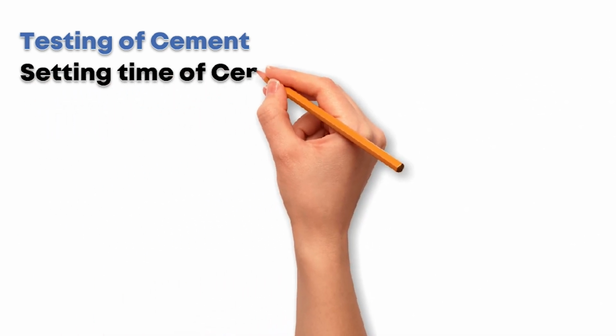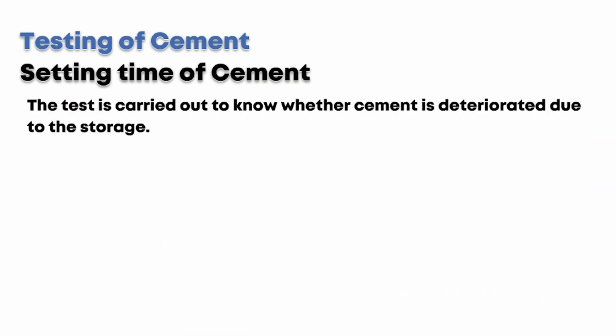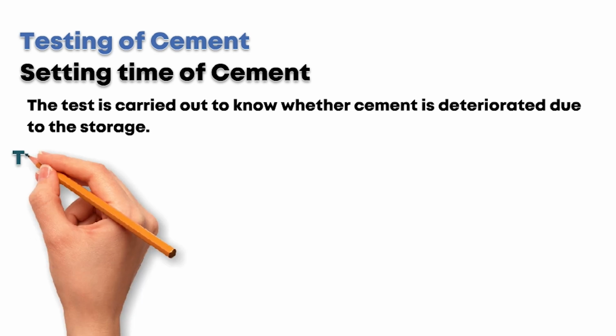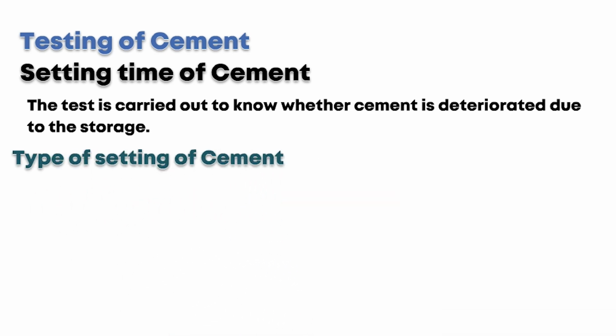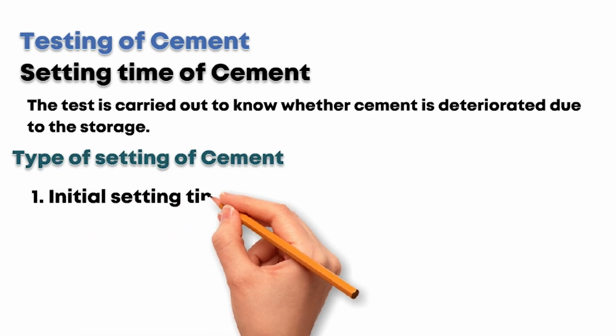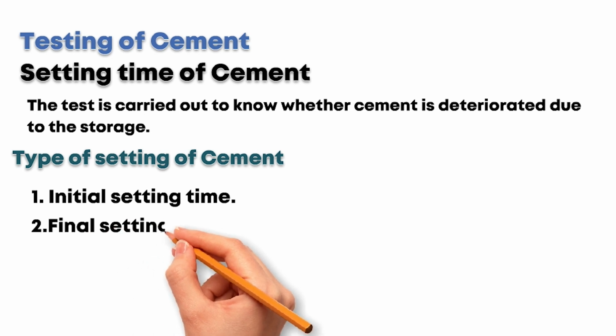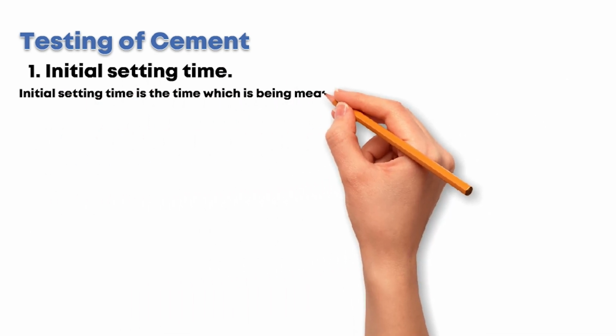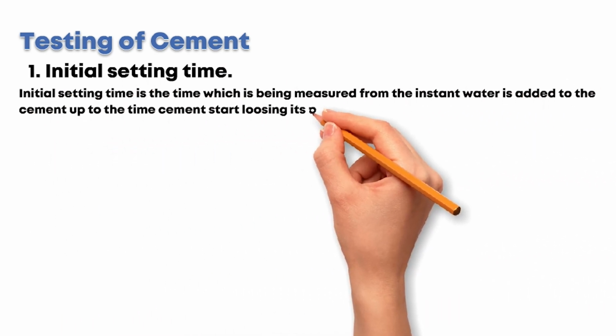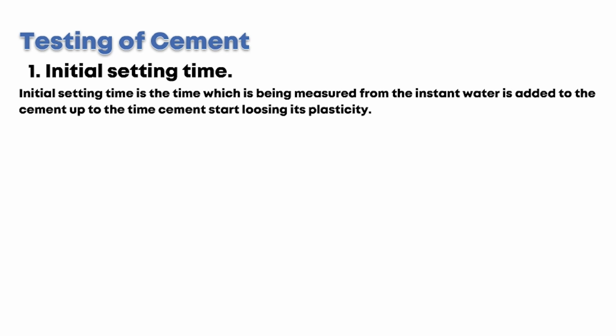Now let's talk about the setting time test on the cement. The test is carried out to know whether cement has deteriorated due to storage. 2 setting times are associated with the setting of cement: 1. Initial setting time. 2. Final setting time. Initial setting time is the time measured from the instant water is added to the cement up to the time cement starts losing its plasticity.